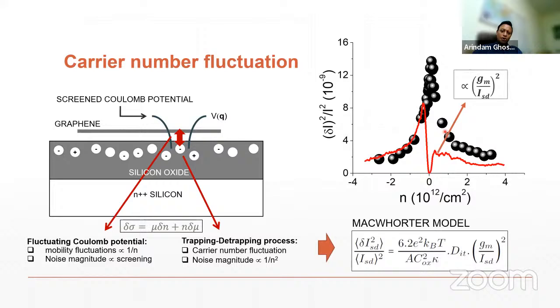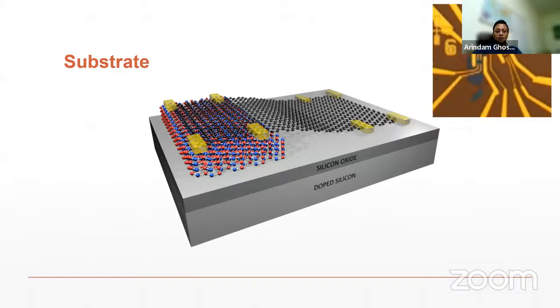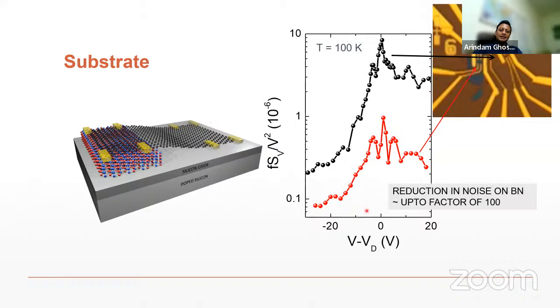So the calculation fits more or less well with the experimental observation, but it fails near the Dirac point, and I'll show you how. And we have been looking at it. The first question that we ask: in order to reduce noise in graphene, how can we change the substrate? This is something which we did a while ago. Part of the graphene was kept on boron nitride, which is another two-dimensional material, but it gives you a very nice single crystal substrate as opposed to an amorphous substrate of silicon oxide. And you measure noise from this part as well as this part. And you can see that the noise when the system is sitting on boron nitride, which is this red part, is approximately 10 to 100 times smaller than that part which is sitting on silicon oxide.